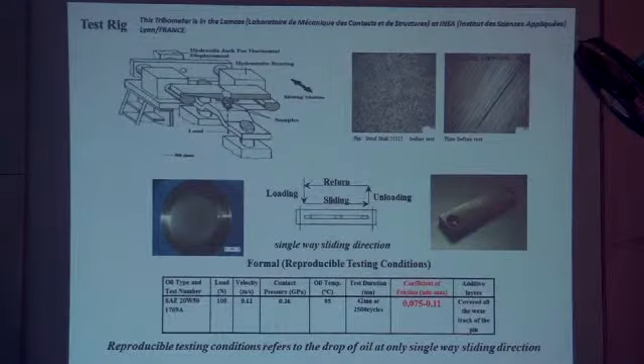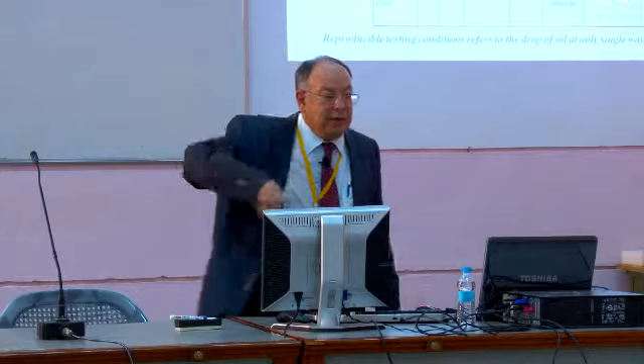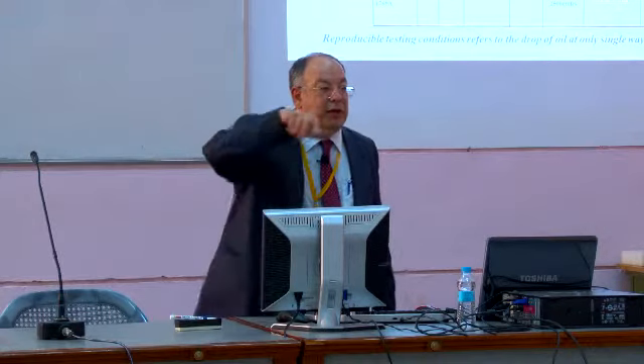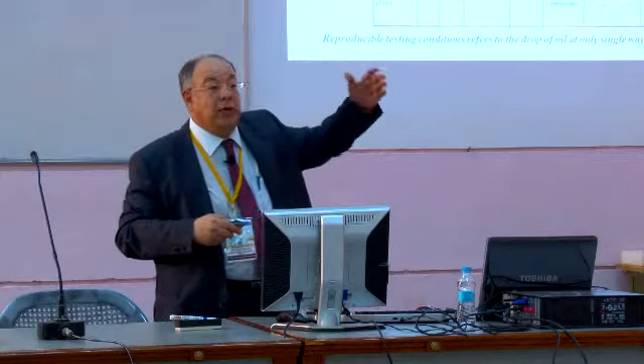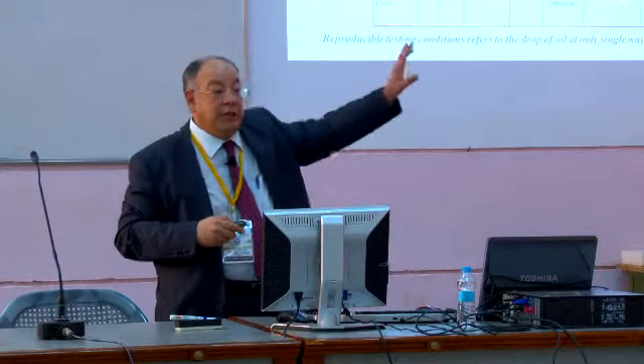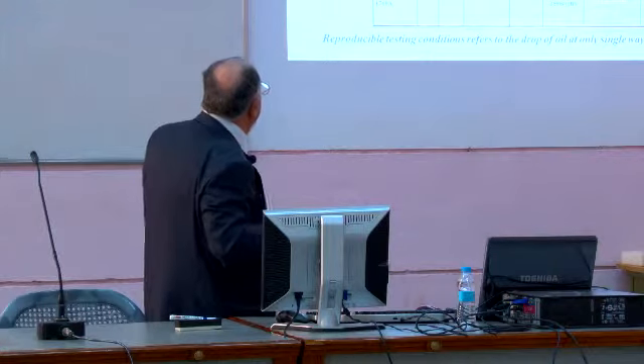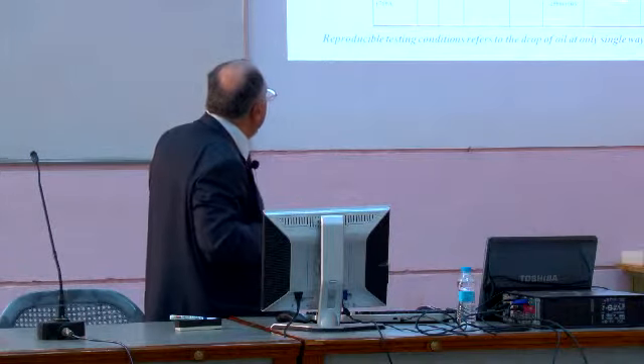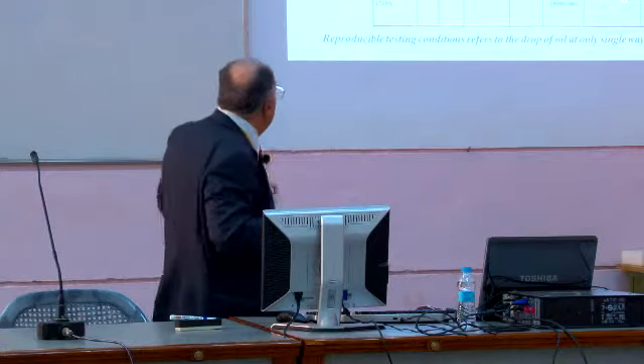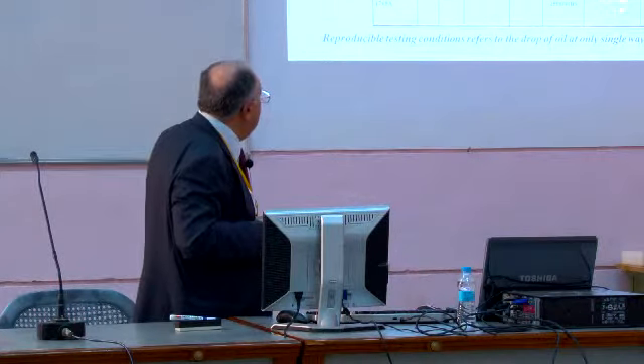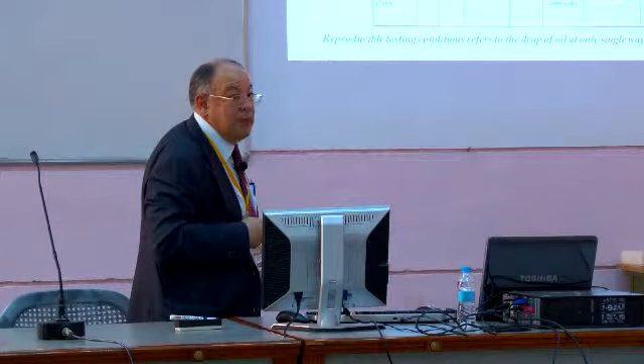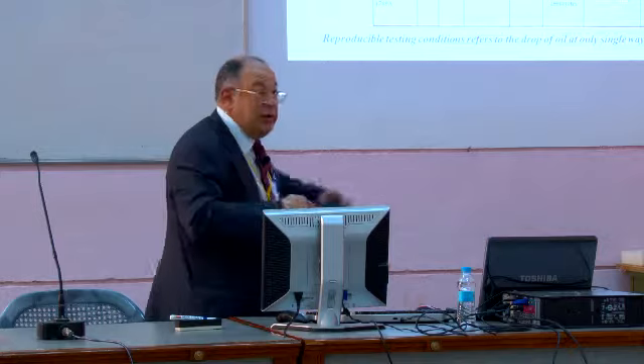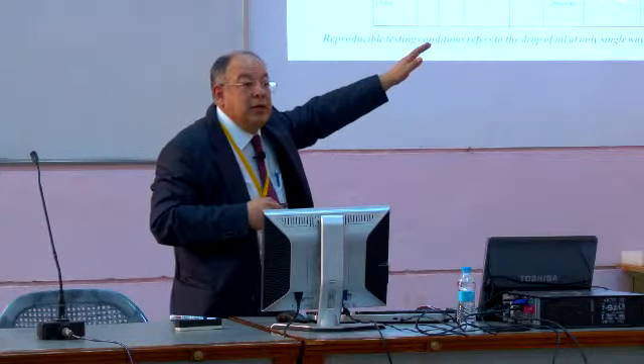With that machine, we found a continuous way, because it's loaded, unloaded, loaded, unloaded. Every time it was loaded, it was on the single way. We did many tests, step loading, dropping the oil, etc. - only 3 drops of oil, 1, 2, 3, then you make a line. Under those conditions, we arrived at almost 0.11, and we obtained a fully covered pin surface layer.